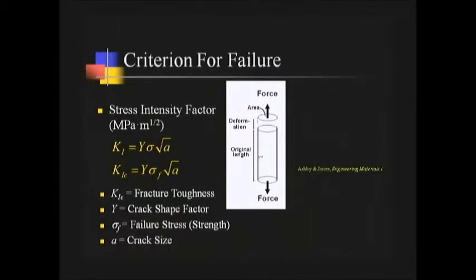And so we have sigma, which is usually used to represent the stress on the material. And some people think that each material has a certain stress level or strength that it will typically break at, and you're probably realizing by now that is not actually the case. A material does not have failure stress as a material property, but rather there is another thing that defines the fracture, and that is the stress intensity factor. A material has a critical stress intensity factor at which failure will occur, and the size of the cracks in the material will determine what stress level is necessary to cause the stress intensity factor to reach its critical level, which we abbreviate with K1C, and we also call that the fracture toughness.